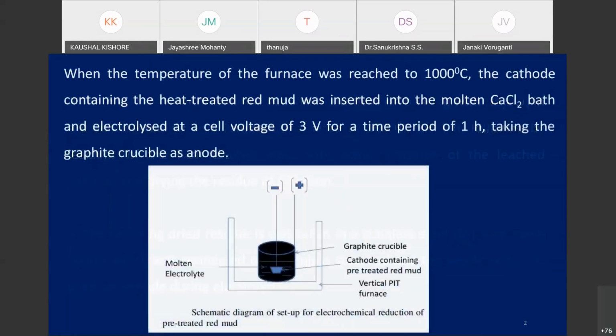This is the figure. You can see it is a basket structure where we have kept the pre-treated red mud, and it is connected to the current collector. The current collector is connected to the negative terminal of the DC source, and the graphite crucible is connected to the positive terminal of your DC source. And then there is the molten electrolyte.